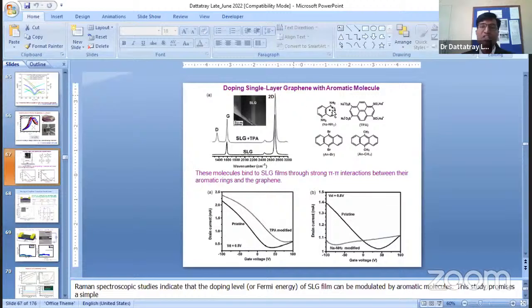For example, these are some of the aromatic molecules. What happens? These molecules bind to the single layer of graphene through strong pi-pi interaction between their aromatic rings and the graphene. For example, this is pristine graphene, this is the TPA molecule, and when you add some other molecule, you can see whether your graphene becomes more p-type or n-type, and you can monitor it again using single layer graphene. See, this G band is very sensitive to surface modification. Any small change on the surface of graphene immediately shows a change.